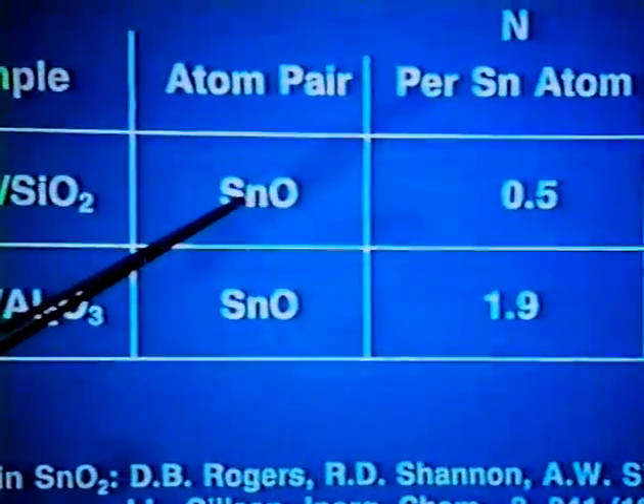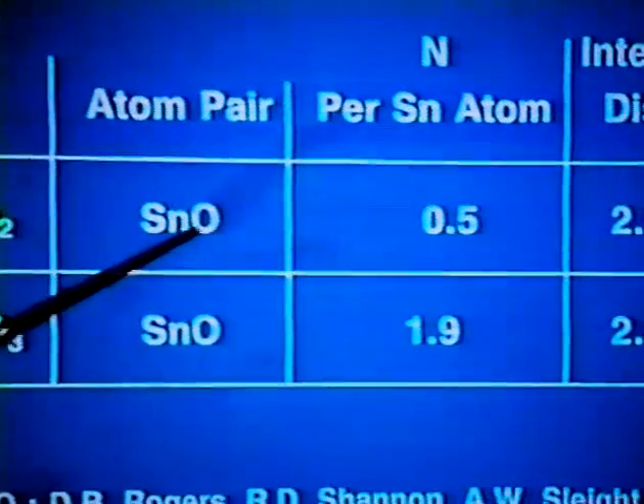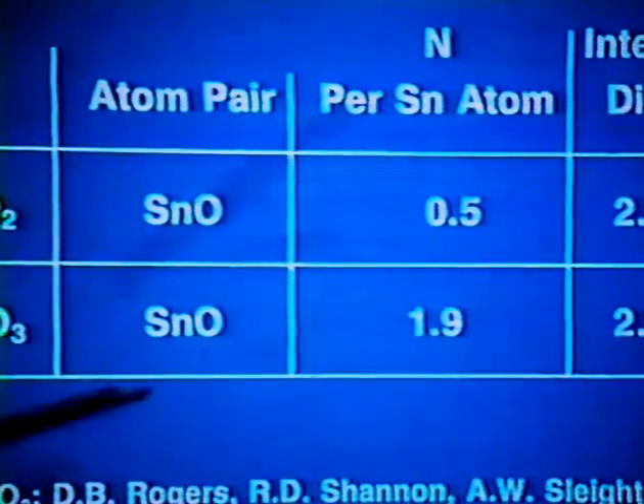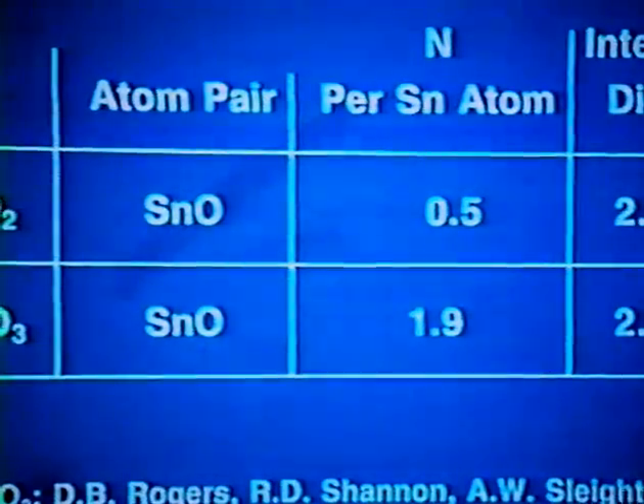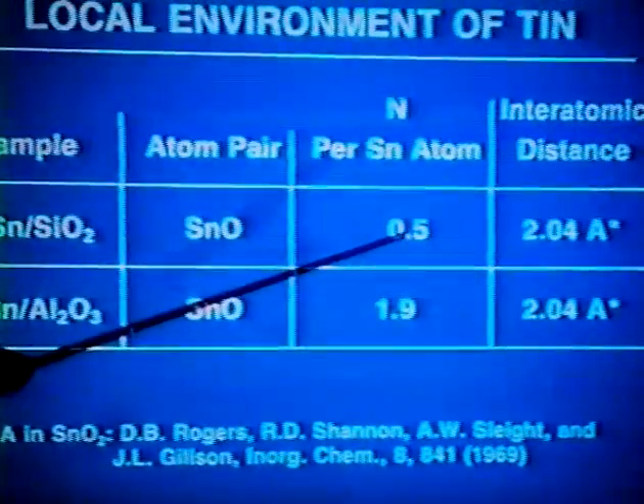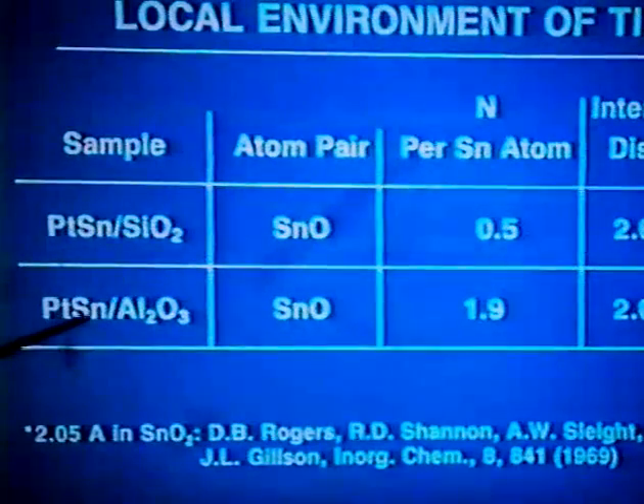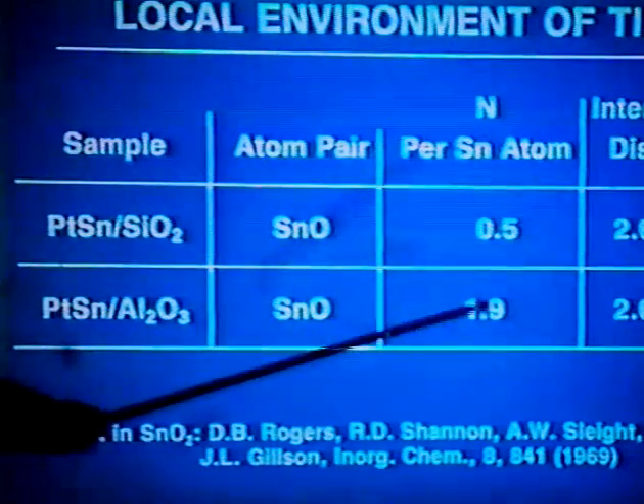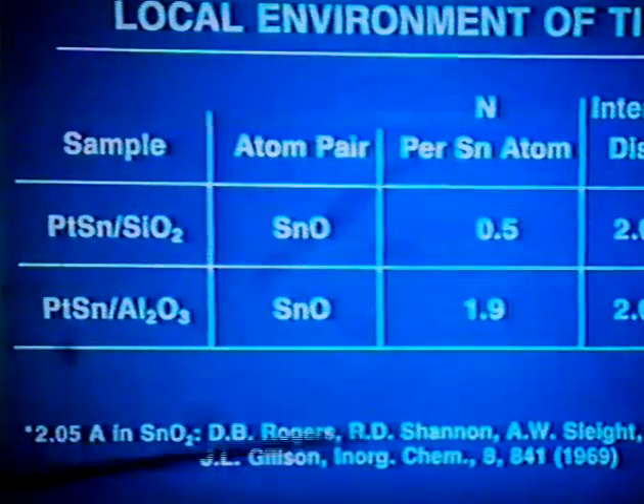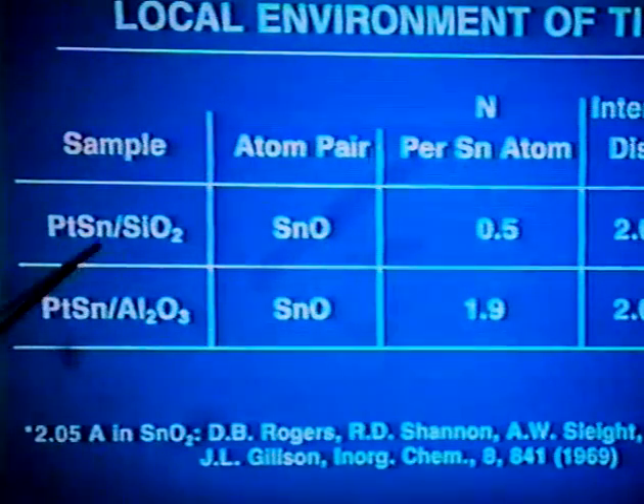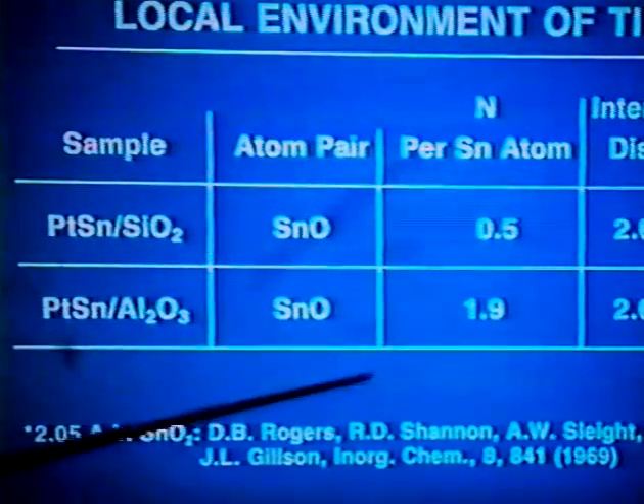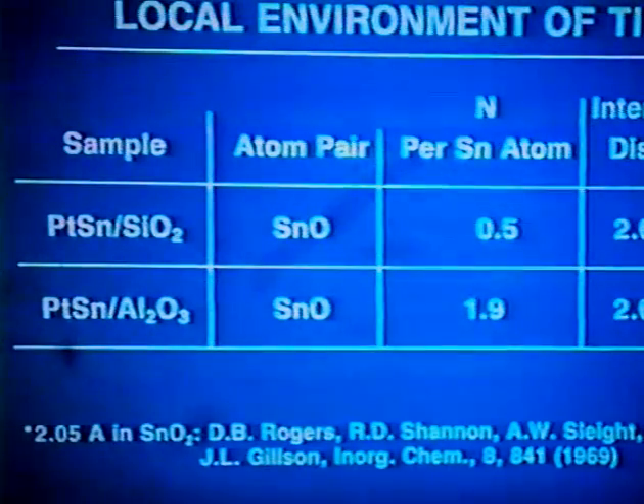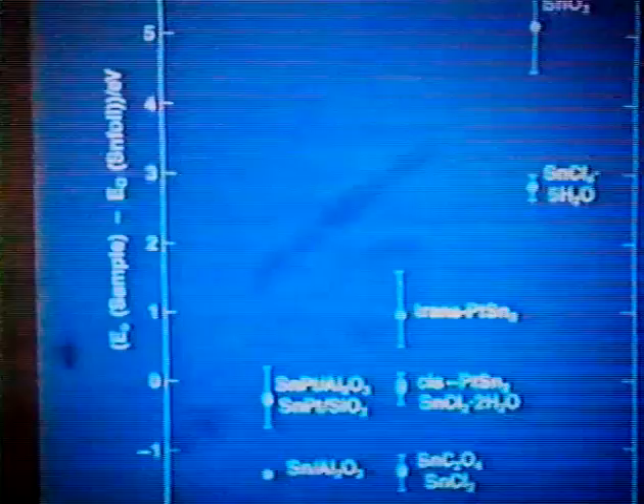Okay, we look at the Sn-O atom pair, the oxygen neighborhood of tin, looking for oxygen in these two samples. We find that in this sample, the silica supported, where there are a lot of platinum atoms in the neighborhood of tin, there are very few oxygen atoms in the neighborhood of tin. In this sample, where there are very few platinum atoms in the neighborhood of tin, there's quite a lot of oxygen in that neighborhood. Well, what are we saying here? We're saying that in the silica-supported sample, the tin has gotten reduced and formed intermetallics with platinum. And in the alumina-supported sample, the tin has resisted reduction, and it has a more or less acidic environment. Next slide, please.